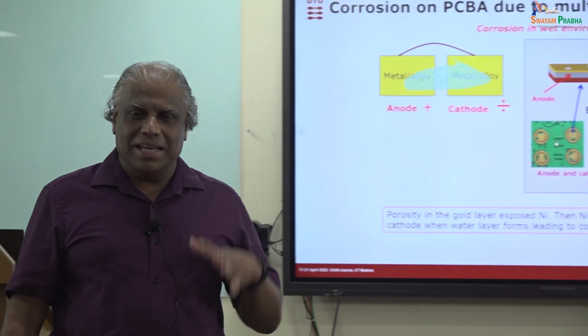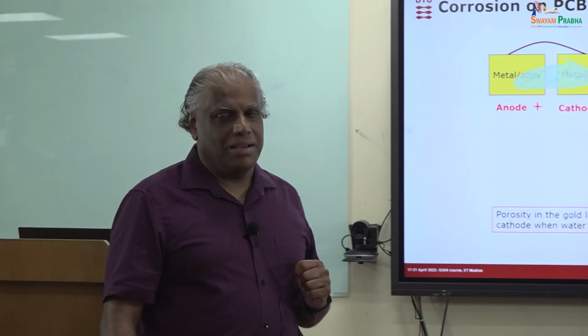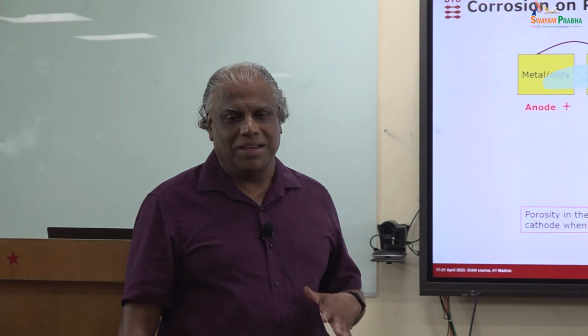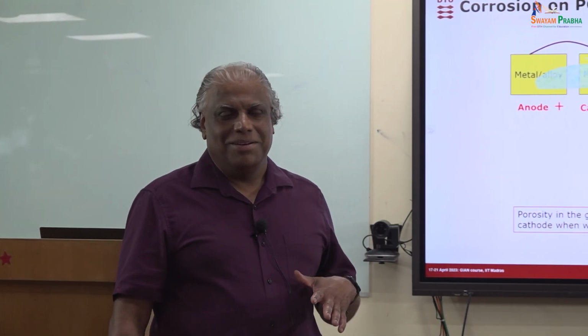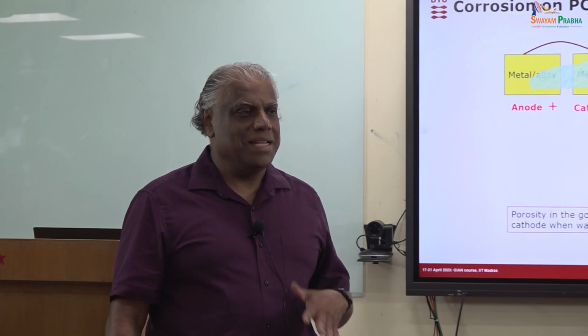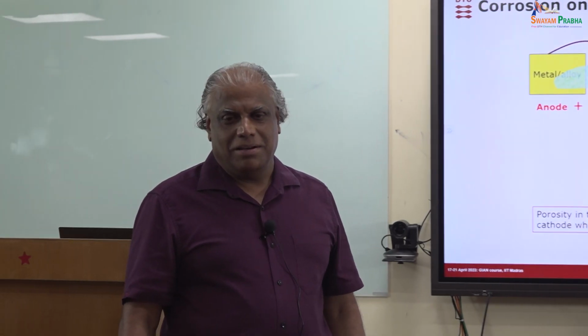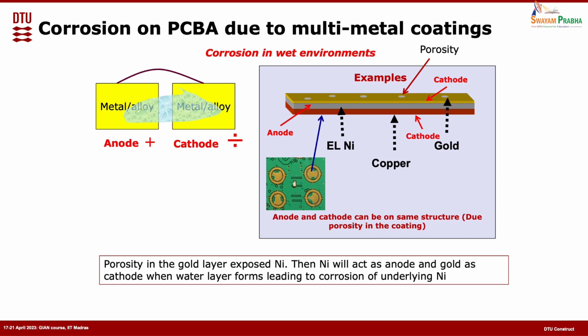So that's the reason that anywhere they use gold in electronics, if it is going to be on copper, you need to have a barrier layer in between, a diffusion barrier layer, that is the electroless nickel. So that's the reason that they use electroless nickel. So that's a typical example of galvanic corrosion. I'll show you more later.